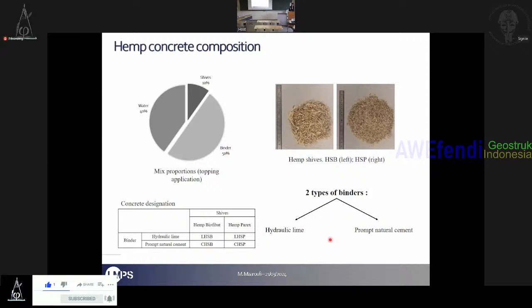Actually, I have 4 different materials or formulations. I mixed 2 binders, hydraulic lime and cement, with 2 different shives. So each time I have lime plus this shive and lime plus that shive, and the same thing for cement. And the shives, are they binder or aggregate? No, these are the aggregates. So the binder is simply lime and cement.